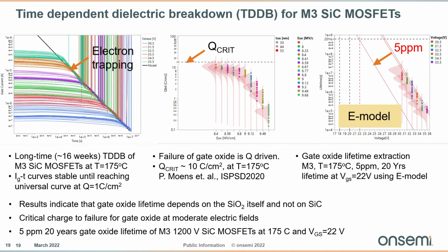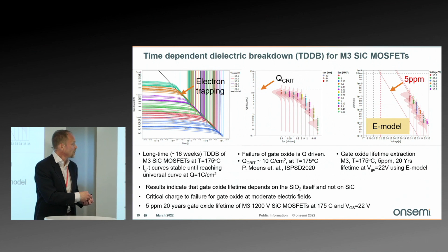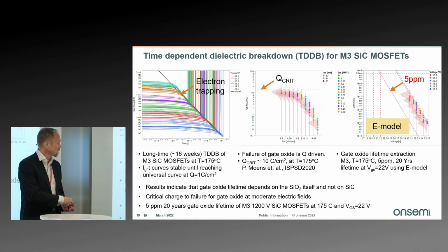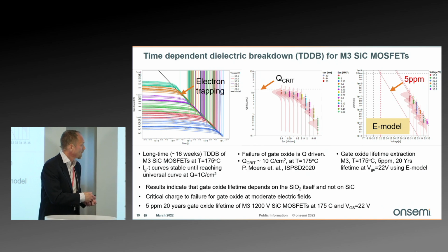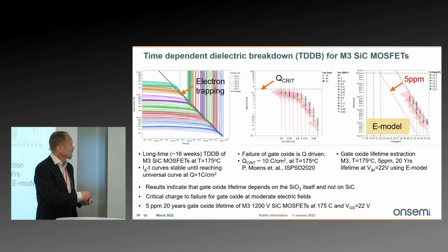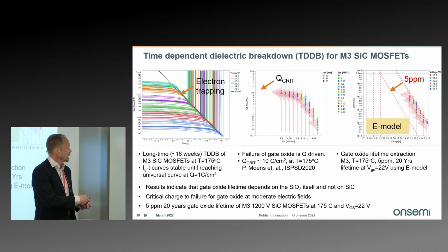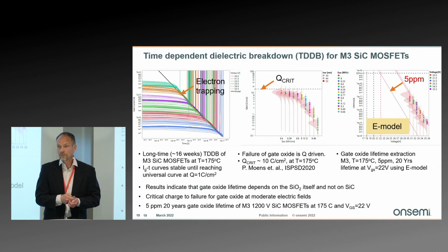charge to failure here. And from this, we can determine the time to failure versus voltage. Given the distribution here, we can extract the lifetime with 5 ppm. So it's about 20 years, 5 ppm lifetime at max rating 22 volts here. And these tests take a long time, up to 16 weeks here in the furnace.